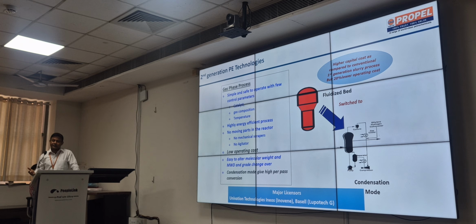In the Sclairtech technology, which is older, you have to use adsorbent bags for catalyst removal, and after 2 to 3 days, if you are not getting the desired color index, you have to change the entire bag. So that is a concern. It's a time-taking process. In the gas phase process, you don't need such a setup. It is easy to tune the molecular weight and molecular weight distribution.